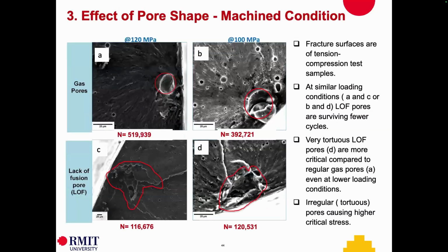Then look at this one. We are almost closing. One point we often ignore in fatigue performance, particularly for additive manufactured cases, is the shape effect, which we found to be critically important, which is often not considered. Look at these two cases. On the first row, we have gas pores compared with lack of fusion pore at a low stress level, 120. A lack of fusion pore, which was the critical defect, produced a fatigue life of 100,000, whereas the gas pores produced 5 times more. The same happened at the lower stress level, lack of fusion pore and the gas pore. With the gas pore, fatigue life is at least 4 times.